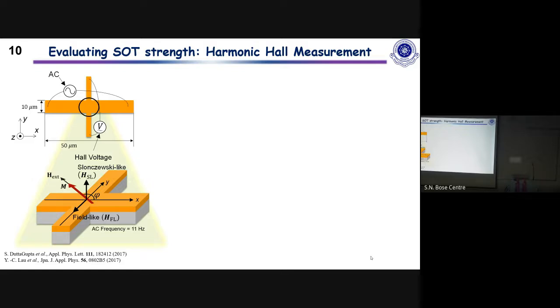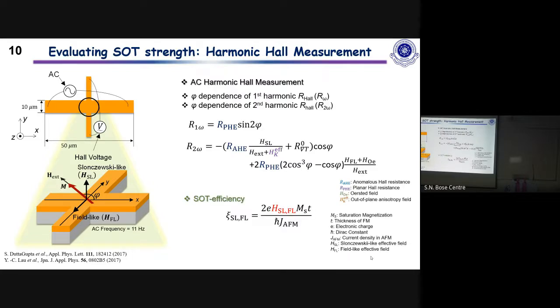So we use this technique. We made these Hall bars with photolithography. They're pretty big devices. And what we actually do is the following. We first saturate the magnetization, which is lying in the plane, and we apply a magnetic field. We rotate the magnetic field in the plane of the sample.